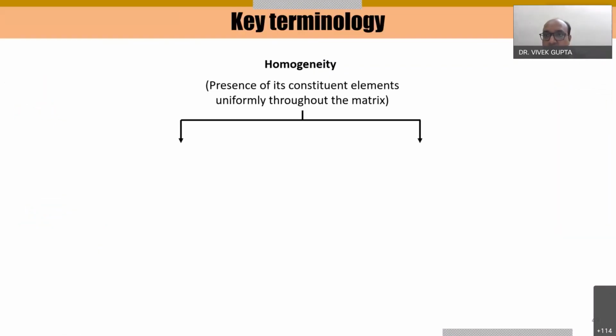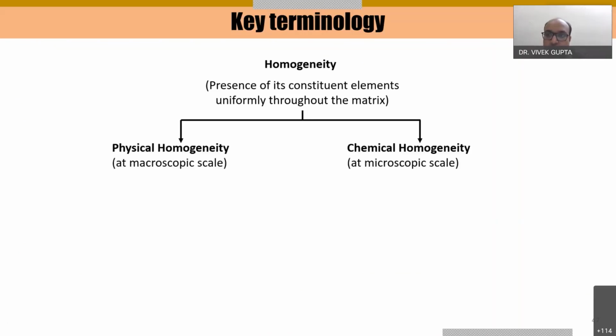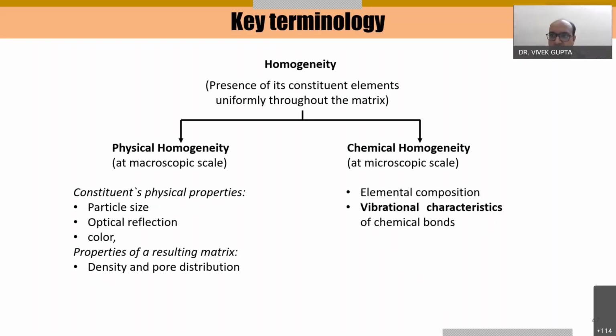What is homogeneity? You can understand it as the presence of its constituent elements uniformly throughout the matrix. I categorize this in two parts: physical homogeneity and chemical homogeneity. Physical homogeneity, which we generally observe in concrete or our products, is observed at the macroscopic scale. We generally use physical characteristics like particle size, optical reflection or color, or tests like UPV, density or pore distribution of the resultant matrix. Either we identify based on the particles, or we do tests on the resulting matrix.